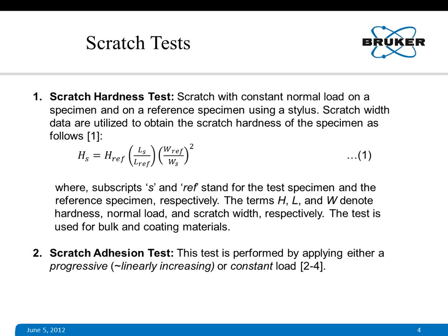Those who are interested can refer to ASTM standard G171. In this scratch hardness test, what we do is basically you take a sample and a reference sample. Sample of coating or bulk materials, you use a stylus with certain load and scratch with a constant load. Make a scratch. Measure the scratch width on the specimen. You repeat this test on a reference specimen whose hardness is known, say for instance fused silica or some other polymeric material for low hardness specimen, and use equation 1 to obtain the hardness of the specimen.